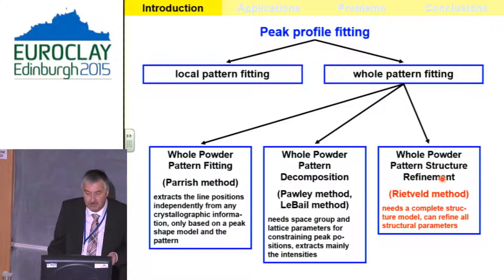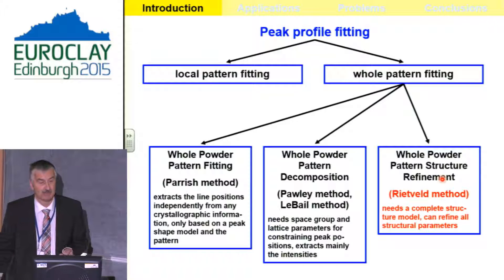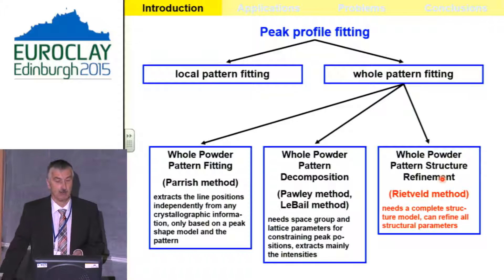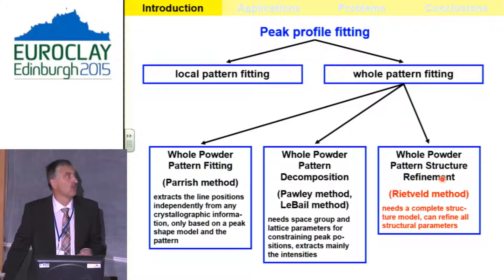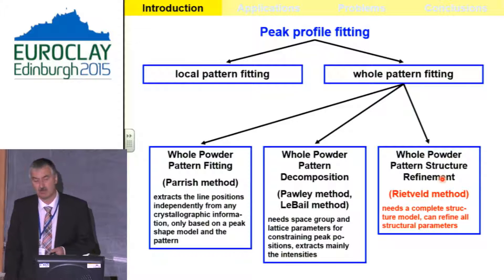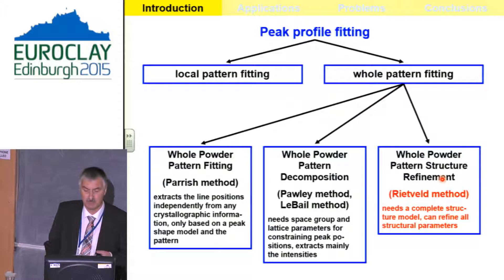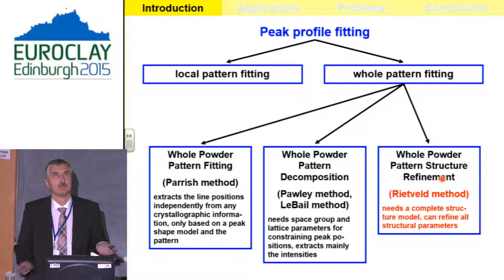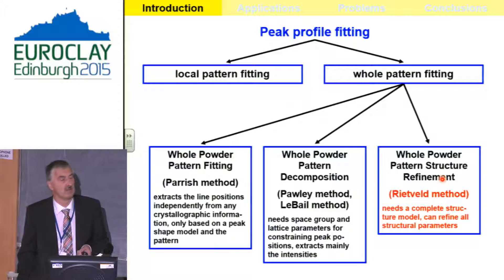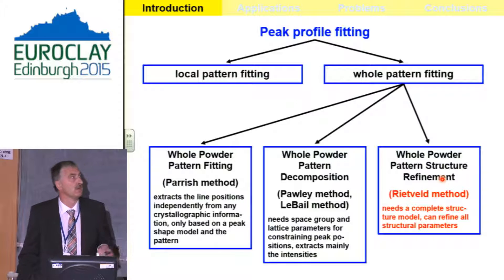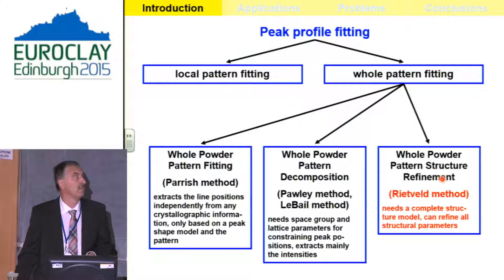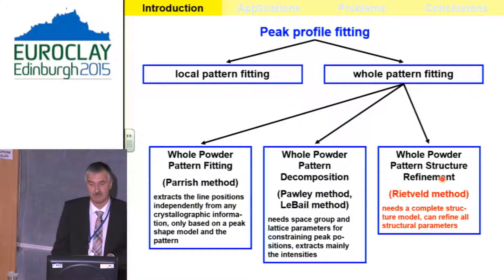The Pawley or Le Bail method introduces some constraints to calculate a certain number of peaks at some number of positions, but the intensity is a free parameter. The whole powder pattern structure refinement — what we call the Rietveld method — can be defined by the need of a complete structure model. In principle it can refine all structural parameters. There are transitions to other methods, because Rietveld programs also commonly allow Le Bail fitting.